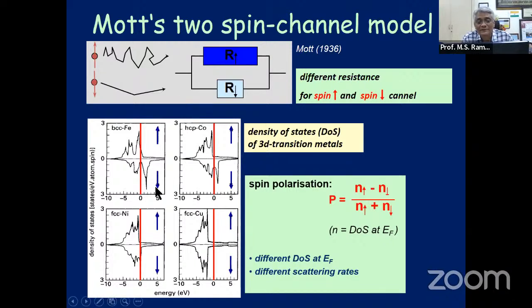You have systems that are highly spin polarized, marginally spin polarized. Iron, cobalt, nickel, and copper are marginally spin polarized, where the spin polarization is anywhere from 11 to 40%. But you also have compounds like chromium dioxide, which should give you 100% spin polarization. Half-metallic alloys give a very high degree of spin polarization.